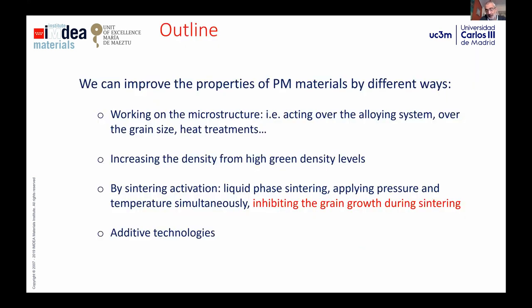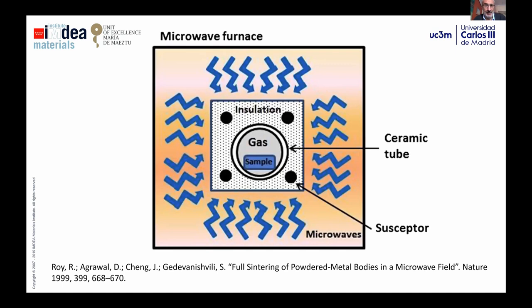So we have other ways to improve the properties in powder metallurgy. One is to try to inhibit the grain growth during sintering. There is one method in which you can inhibit the grain growth, which is the microwave furnace, with microwave sintering. Microwave sintering was applied for ceramics before the year 2000, but from 2000 methods were developed for sintering in microwave furnaces even metals.